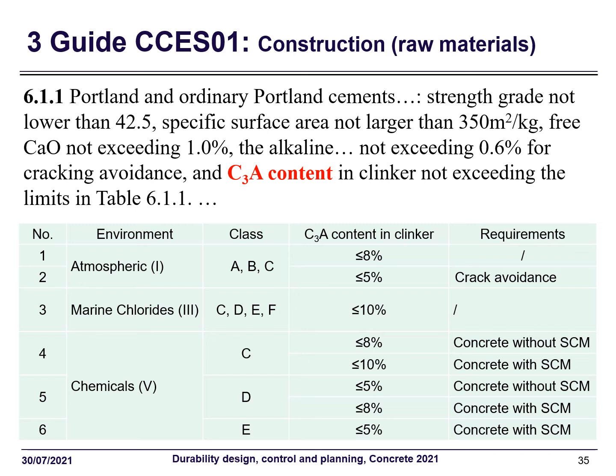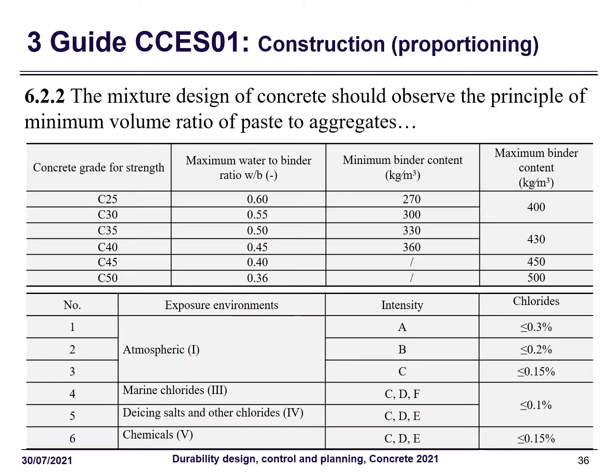On construction, first is on the raw materials. Here I give you the article concerning the Portland cement. You can see that we put some requirements on the characteristics and composition of the cement, and some environment-dependent requirements on C3A, for example, with respect to the environmental type and exposure classes. And then we give some instructions or requirements on the proportioning. For example, for a different grade of concrete, we impose the maximum water to binder ratio, and the minimum and maximum content of the binders. We impose also the limitation of chloride content with respect to the different environmental action, meaning type and intensities.